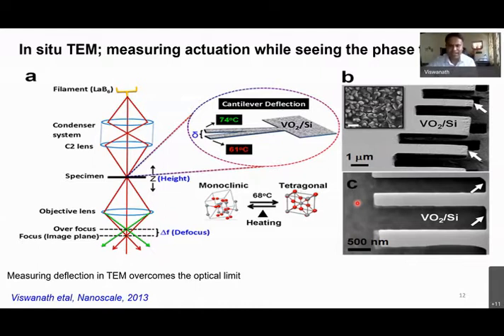I was initially puzzled. Is there any thermal vibration, noise playing a role, and so on? But later on, I understood, of course, it is the thin film stress that we measured that is probably contributing. Your TEM sample is almost acting like a cantilever. Then finally, I decided to make a cantilever of vanadium dioxide deposited on the silicon substrate.